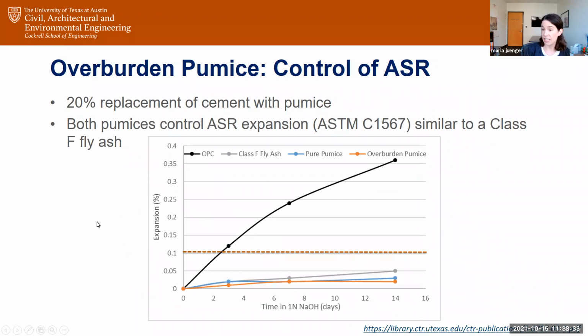Another example test of what people are looking for when they're looking at supplementary cementitious materials is how they help concrete durability. So in this particular example, for alkali silica reaction shown here, it's a reaction that causes expansion and cracking in concrete. In this Portland cement, you're getting a high expansion on your y-axis over time. But when you replace Portland cement with pumice, fly ash, they all reduce expansion. So the pumices perform quite similarly to the fly ash, even the overburden material. So it proves to you that the concrete industry can take the rejects from other industries quite easily and don't have to use their more pure products.